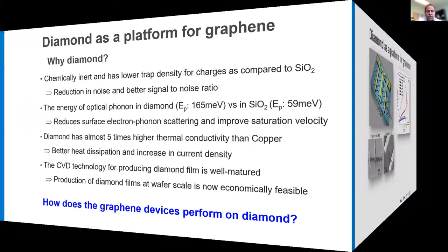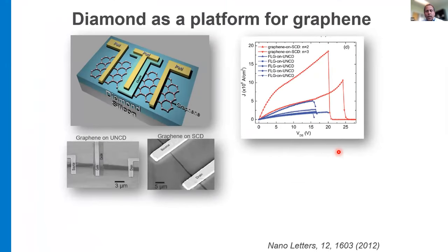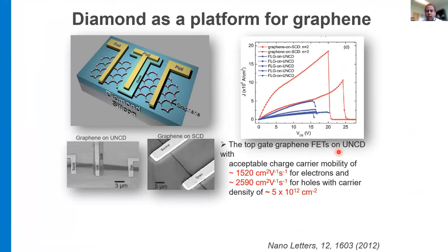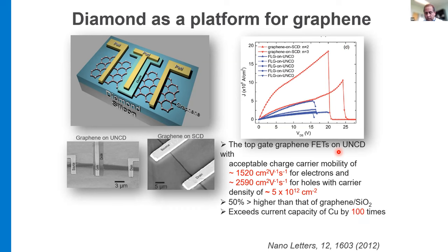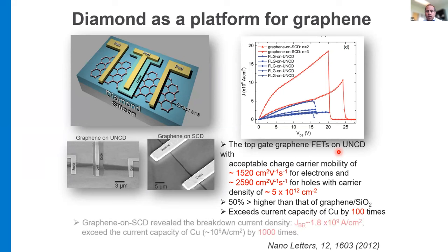So the question is how these graphene on diamond devices perform. These are two terminal and three terminal devices that we fabricated, including the field effect transistors. And we got very good mobility for the electrons and holes with the carrier density, and this is at room temperature. But when we look at pushing the current through this graphene ribbon, we get very high current density. In the case of a single crystal diamond, we're able to get the breakdown current density up to 10 to the 9 amps per centimeter square, which is pretty high. It's almost like superconducting wires, but at room temperature. And so this exceeds the current capacity of copper by like 1,000 times.